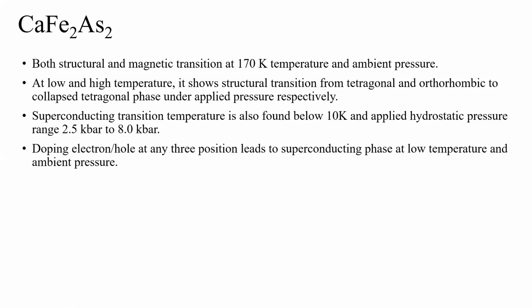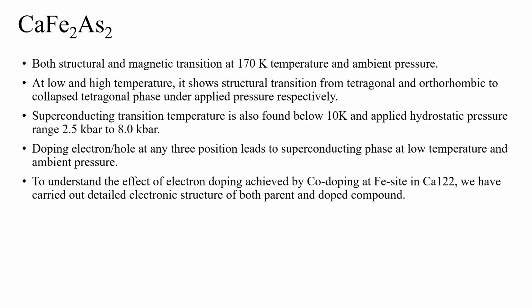Doping electron or hole at any of the three positions. Electron or hole doping means you replace the iron, arsenic or calcium atom with similar radii atoms. In these conditions, you can also get a superconducting phase at low temperature and at ambient pressure. In our case, we chose cobalt doping at the iron site because of obvious reasons. If you dope cobalt at the iron site, you can get very big, high quality crystals, of size 6 to 7 mm by 7 mm. Because of that, we chose this compound.